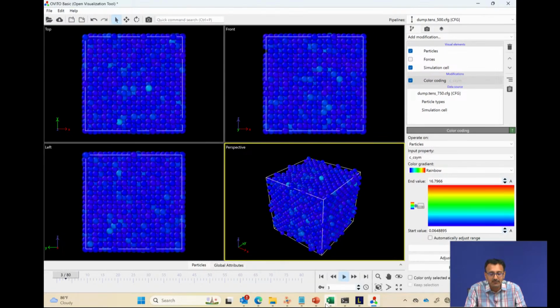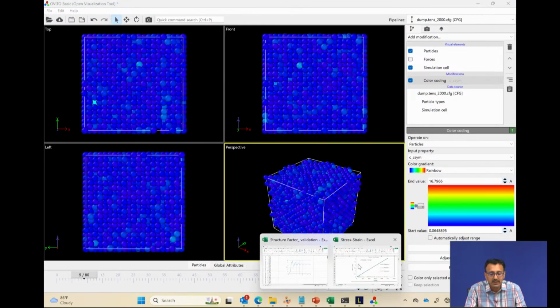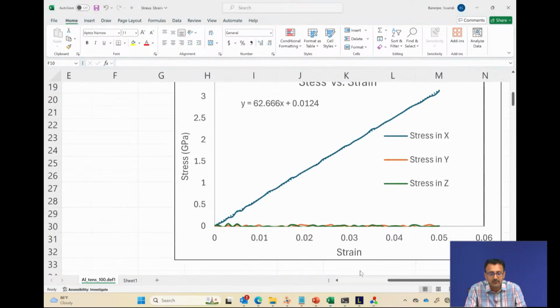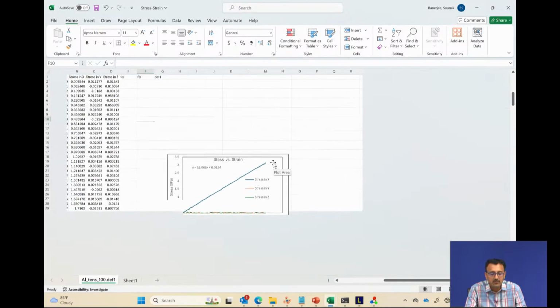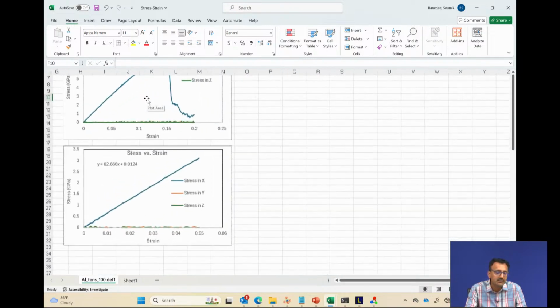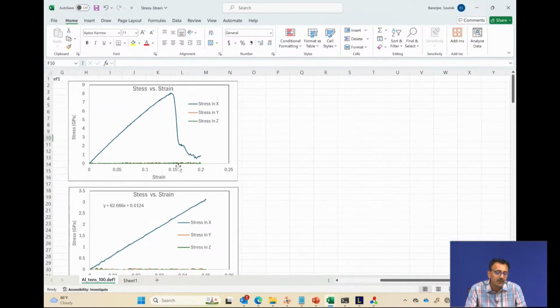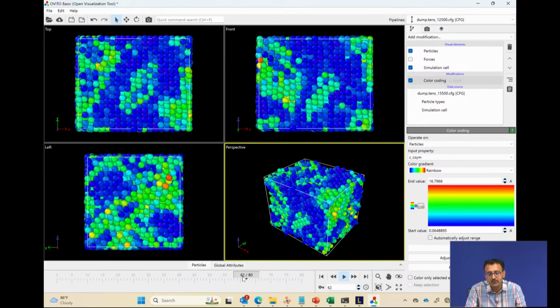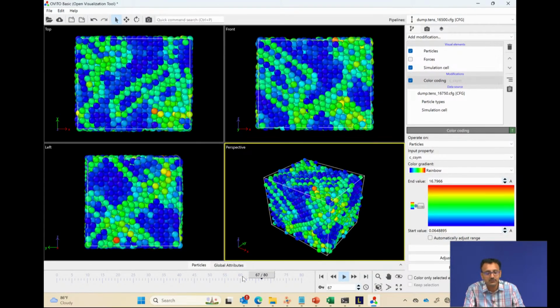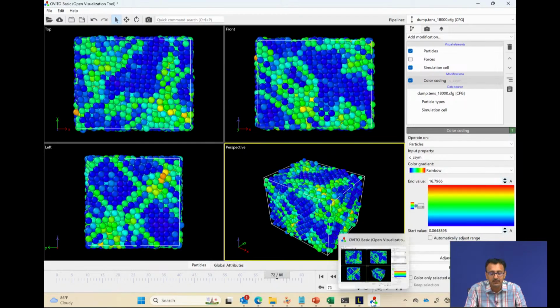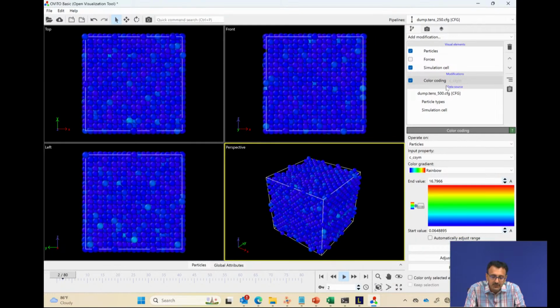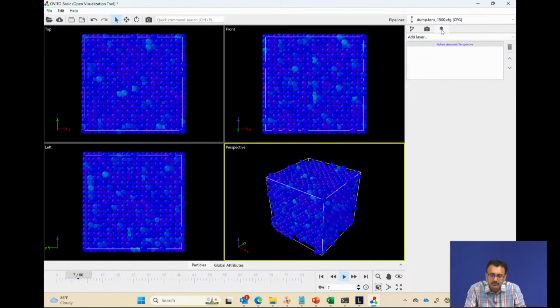And if you look at the trajectory, the stress strain characteristic here, this process starts at about 80% of the simulation has run. There are a total of 80 frames written. So about frame 60 to 64, that's where you start to see the plastic deformation, which is also captured from the stress strain characteristics. So let me see if there is a way to remove.